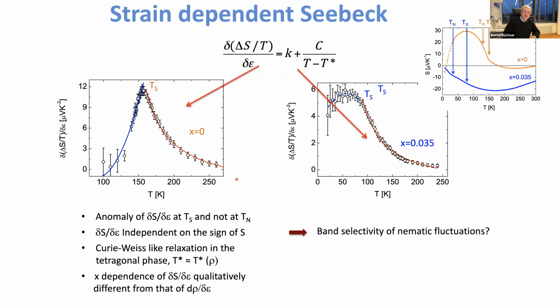So in both cases, we can then now follow the strain dependence of these things. And the first message is it does not change when you change the sign of the Seebeck effect. So that simply means that the strain derivative is independent of the sign of S. And the easiest way to explain this is the band selectivity of nematic fluctuations. So apparently only part of the Fermi surface, if you have these holes and electrons, really feels nematic fluctuations.